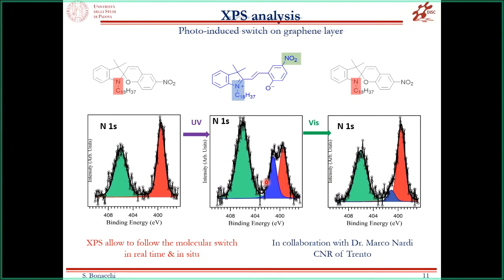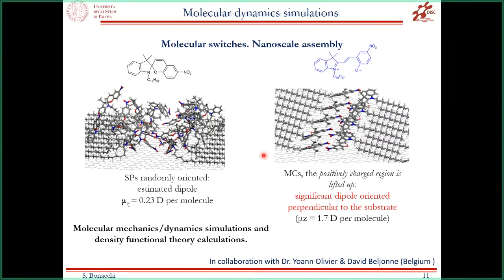So not only are we able to form a highly ordered film, but we are also again able to switch the properties of this molecule. And to understand how these two different forms, the closed one and the zwitterionic, charged one, could induce a dipole moment on the graphene layer on which they are assembled, we also perform molecular dynamics simulation and density functional theory calculation. These prove that the spiropyran form, even if it is able to form an assembled lattice, does not have a real dipole moment on top of graphene. Instead, as soon as we analyze the merocyanine form, the open one, we observe a significant and strong dipole moment oriented perpendicular to the substrate.